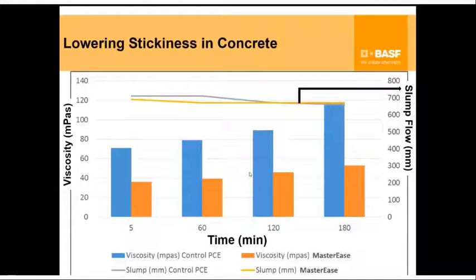And this is not surprising. This is because of a thixotropy buildup that happens in cementitious system over time that increases the inherent viscosity or increases the stickiness in your concrete, even for the same workability level. And what I'm showing here is that with these new types of chemicals, the blue line basically is a typical control polycarboxylate ether type molecule, where you start off with a higher viscosity as shown at 5 minutes in the blue graph, which is about 70 MPas, and it continues to increase over time even though the workability is constant at about 700 flow, right?